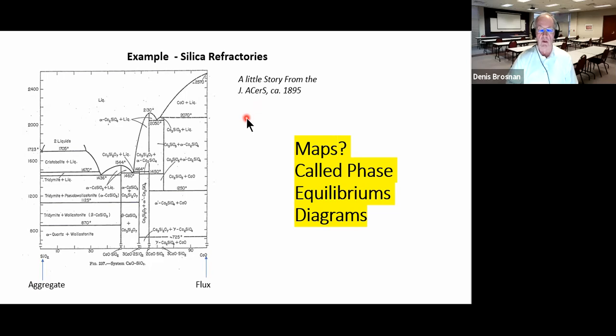And so he would walk out to the mixer when they made a mix, and they might have made one in the morning and one in the afternoon. Remember, the mixers were not electrically powered back then. They used animal power in the mixers. So he took a large container of liquid that was black in color and poured it into the mix. And the mix churned around like a Muller mixer, throwing the material around until the particles of ganister were wet out. They fired the product, and it was wonderful. It was as good or better than the competitors.